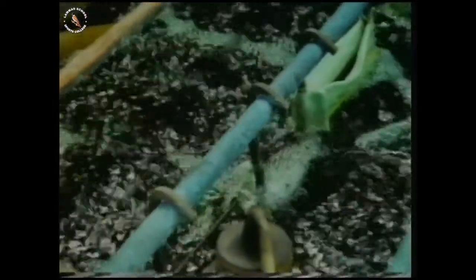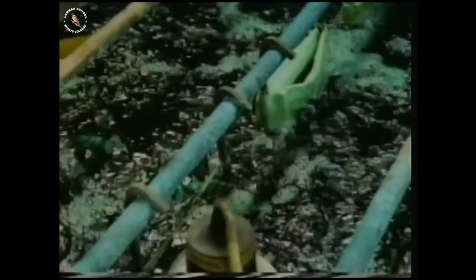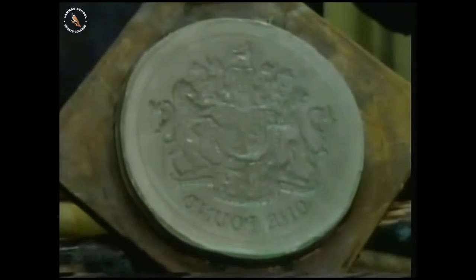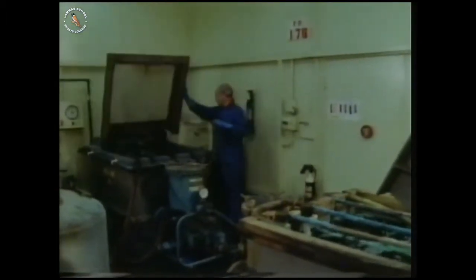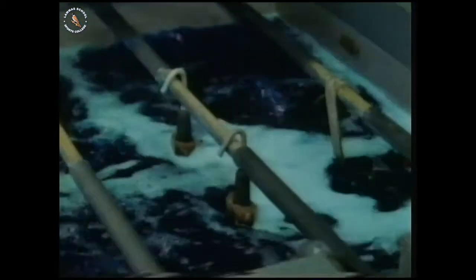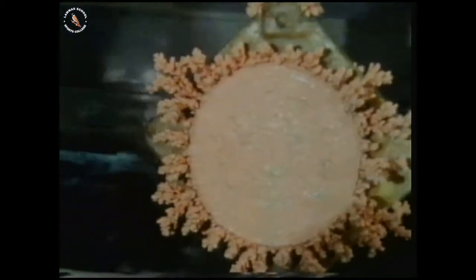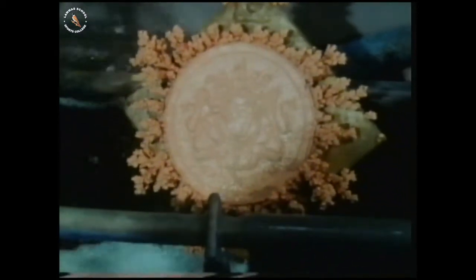The mold now becomes the negative electrode in the electrolytic process that in 2 hours deposits a layer of pure nickel over the mold, 0.05 millimeters thick. This thickness of nickel provides a hard surface, but it wouldn't be stiff enough on its own. So it goes into another electrolyte, again as the negative electrode, but this time for 3 days. The result, 2.5 millimeters of copper on the back of the nickel, which gives it the rigidity it needs.